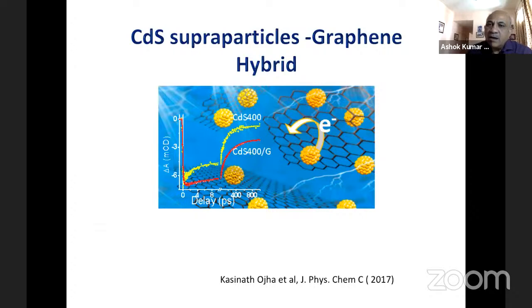Now this is another example of how you can design a much more efficient nanostructured hybrid device. So here what we have done, we have taken some graphene oxide based material on which we have embedded cadmium sulfide supraparticles. Okay, cadmium sulfide supraparticles means, like if you look in the picture, there's a round ball made of very small particles. So each small particle is like a quantum dot, right? And together this large particle is called a supraparticle. This is around 400 nanometers. And each small one is around 5 nanometer particle of cadmium sulfide. And they've joined to form these supraparticles. And you have this particle on the surface of graphene oxide, etc.